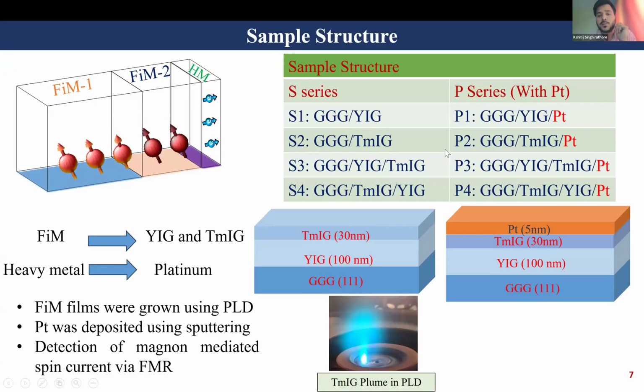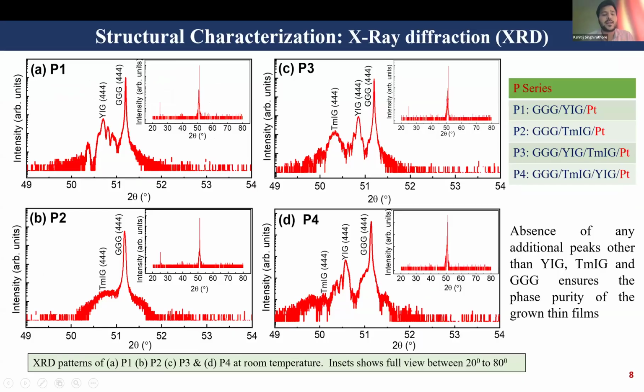Similarly, parallel to the S series, we have a P series, in which we have deposited platinum as a heavy metal using sputtering. These thin films were later characterized structurally using XRD, where you can clearly see the well-grown YIG and TMIG films on the 444-oriented GGG substrate. The absence of any additional peaks apart from the YIG, TMIG and substrate peaks gives us an idea of how pure these grown thin films are.